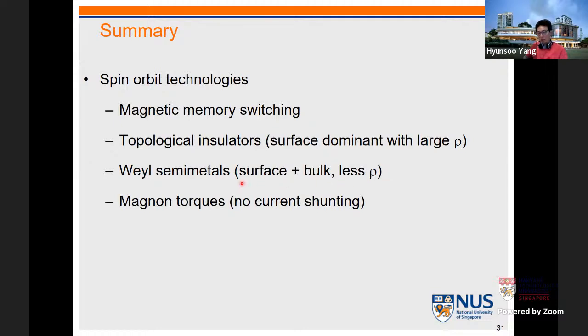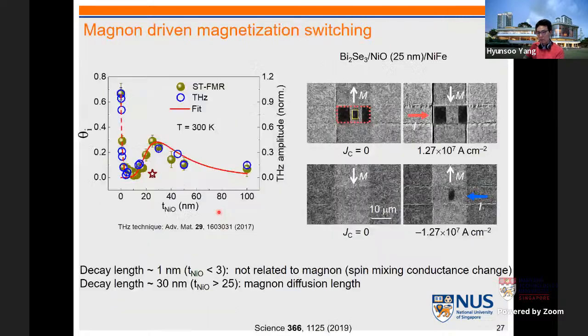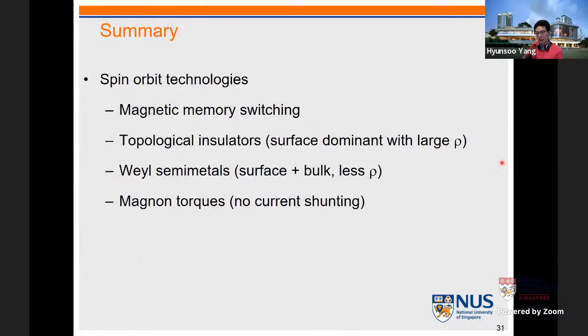So to completely remove this current shunting issue, now we use this magnon torque concept. But the price we have to pay is the conversion efficiency is not the same as the zero nickel oxide case. So if you look at zero nickel oxide, and then look at our maximum data, it is only 50%. By converting from spin current to magnon and magnon to something, because of this multiple conversion, we lose our efficiency to 50%. So the next question is, how do we improve this penalty in future research?